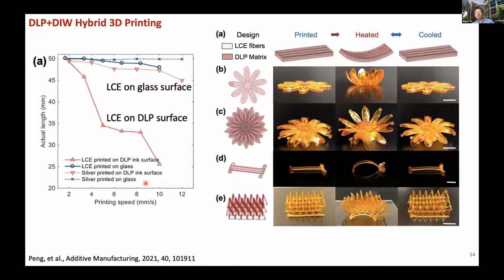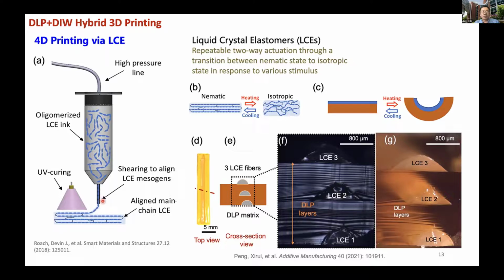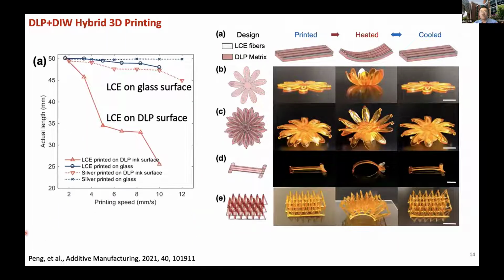But one thing in printing the LCE is that as you extrude it out, the ink, the mesogens, they're all aligned. But you have to fix that immediately. If you don't fix it, it will shrink. So even in the DLP print, as you extrude the LCE out, they are sort of pre-stretched, and so they tend to shrink back. So this is actually making the printing relatively challenging on a DLP printed surface.